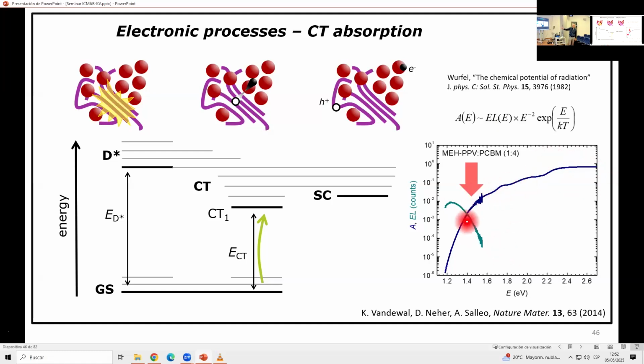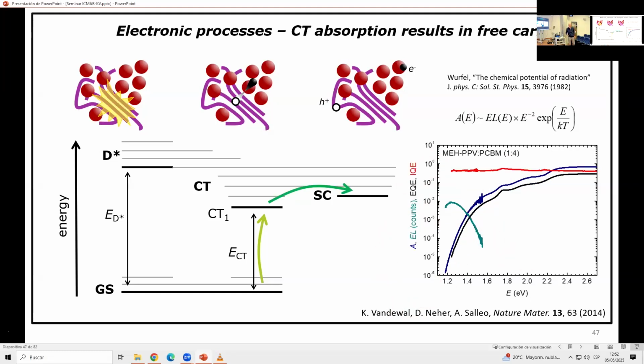And in the meantime, we have extended our absorption spectrum measurement over, you see logarithmic, orders of magnitude. You can measure a photocurrent spectrum and then calculate, once the light is absorbed, what's the chance that you go out? What's the chance that you make free carriers? And you can see, even here, if you excite where it's very weakly absorbing, once it's absorbed, it will split as efficiently as if you would excite only polymer, or only acceptor, or you excite this interfacial state directly. Once you have excited it, splitting it is easy.